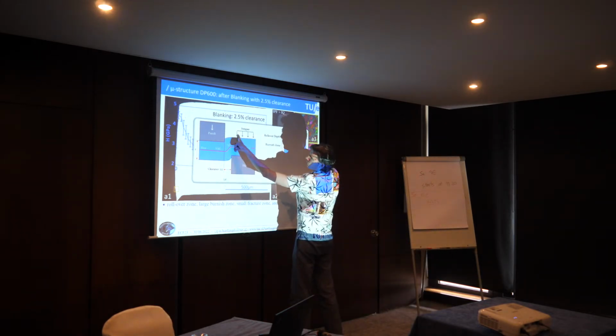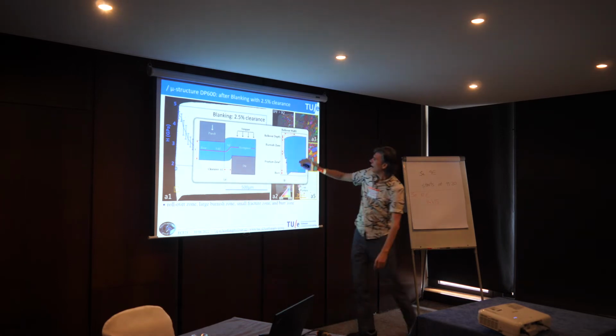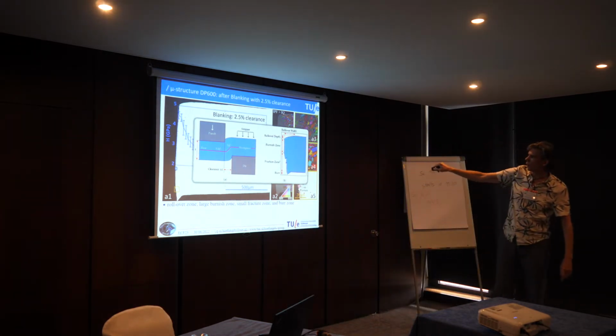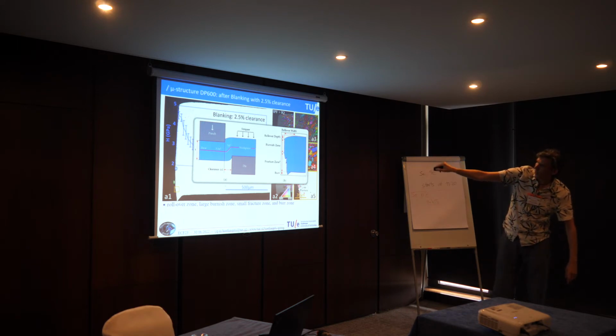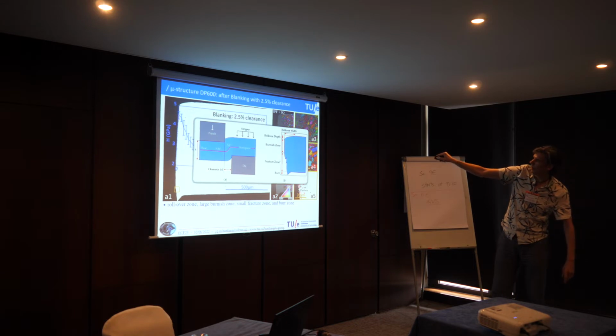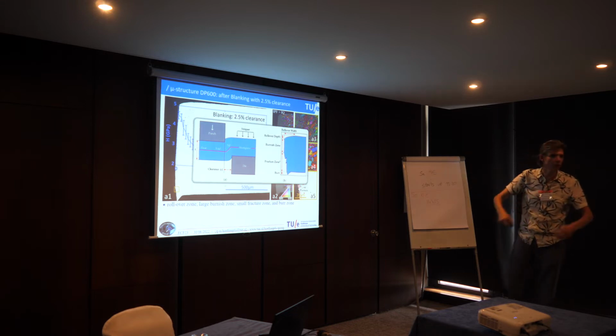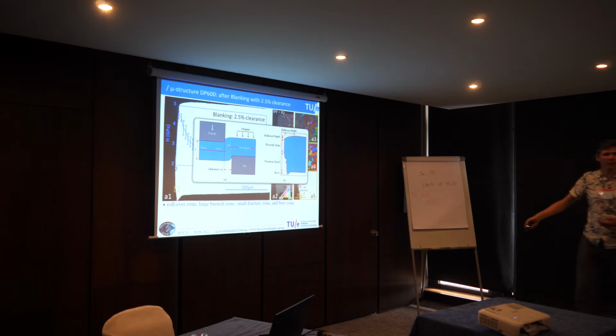and this material is sort of sheared off. And that leads to this kind of cut edge. And you can see actually this cut here, so there's a rollover depth. Here, there's a burnish zone that's going from here to here. There's a fracture zone that's going to here, and there's a buckle. So we see all the common features that you would expect.